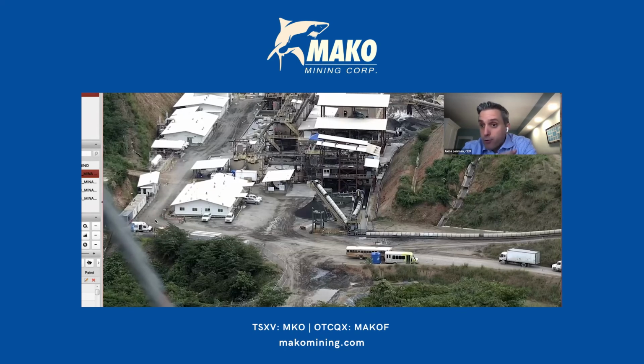It is very fortunate that we had the ability to mine this mine as selectively as we did, because more or less seamlessly we were able to implement all of these processes and procedures and get the right batch recipes going into that crusher and eventually the mill, such that right now our experience with recoveries is back up to about 85%, almost exactly where we would expect to be from a metallurgical point of view.